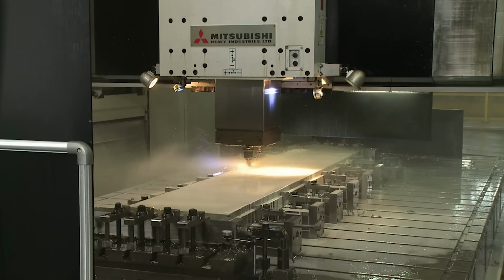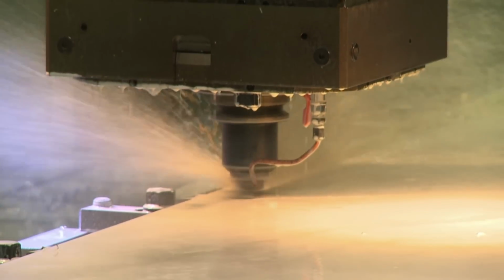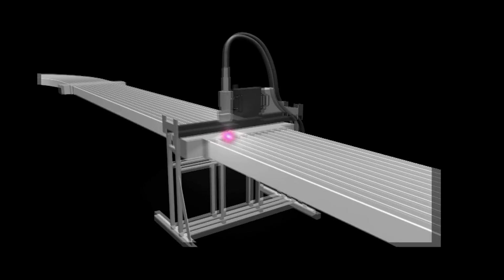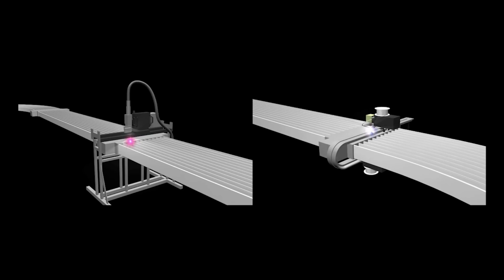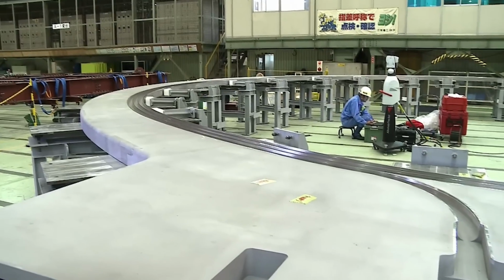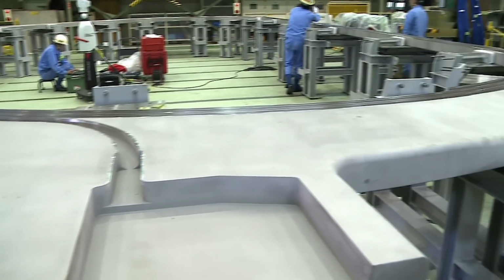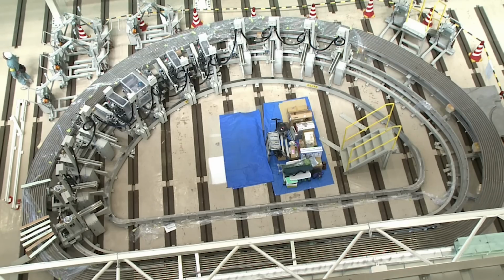The radial plates are gigantic D-shaped stainless steel plates with spiral grooves machined on both sides. They are made of several segments machined and welded together. In Europe, some of them are tungsten inert gas welded, while others are electron beam welded. In Japan, a combination of laser and tungsten inert gas is used. After welding, the final machining is carried out. The length of the groove is up to 750 meters, and an accuracy is required for the groove length of tenths of parts per million.